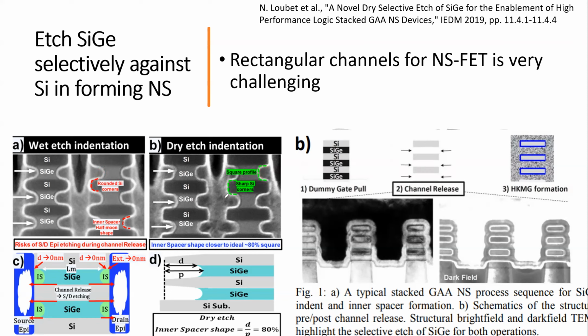You want very sharp silicon corners. That's what you desire. The wet etch won't give you that. Wet etch is not going to give you that. It's a rounded one. The dry etch, yes. If you do a good job, you should have it.